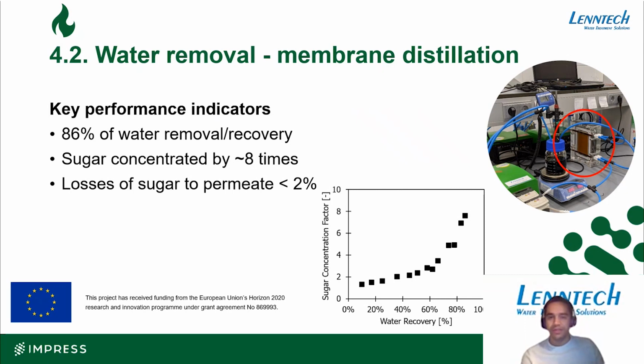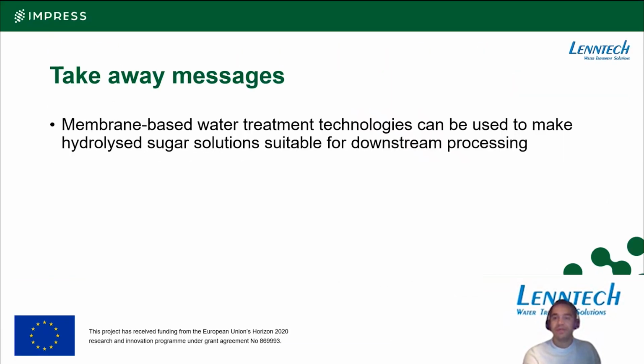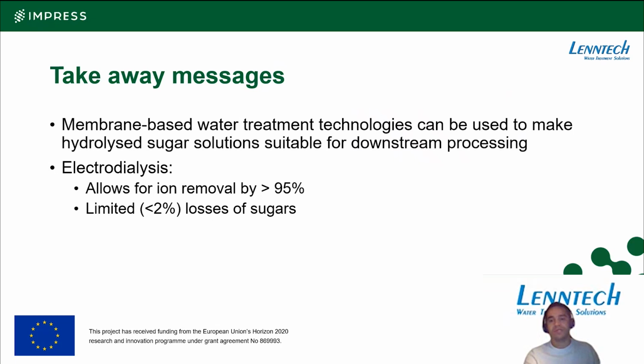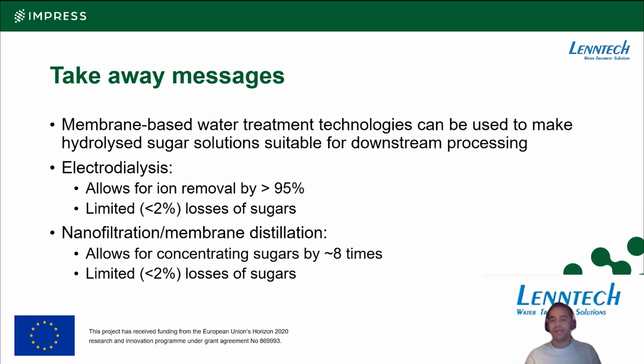So what are the takeaway messages from this part of the webinar? Membrane-based water treatment technologies can effectively be used to make the hydrolyzed sugar solutions produced by Avantium in their Dawn technology suitable for the downstream processing that will be conducted by other partners in this consortium. We can achieve more than 95% ion removal by electrodialysis while only losing 2% of the sugars, and in subsequent nanofiltration or membrane distillation technology, we can concentrate the sugars by approximately 8 times, while again limiting the losses of sugar to 2%.